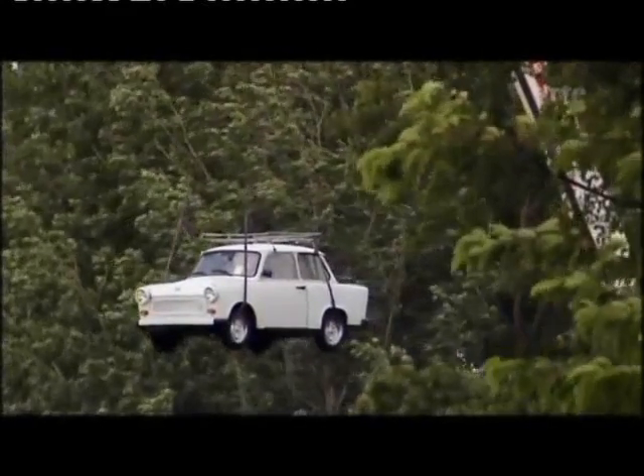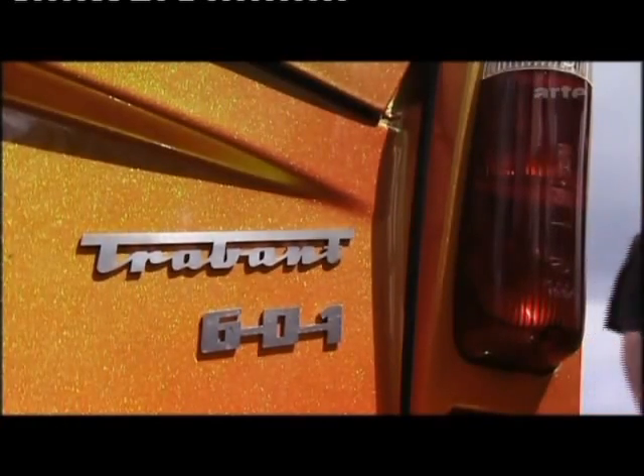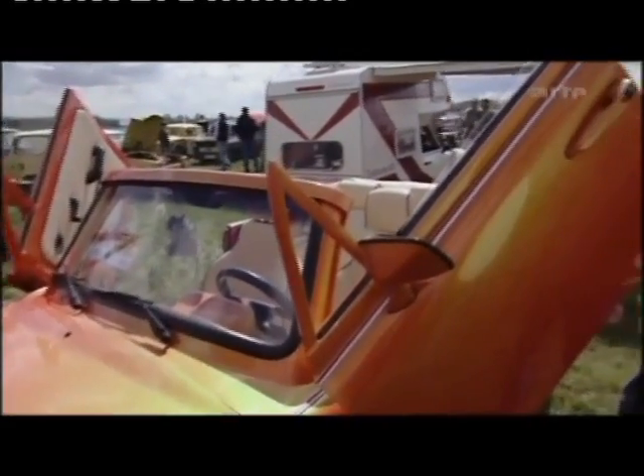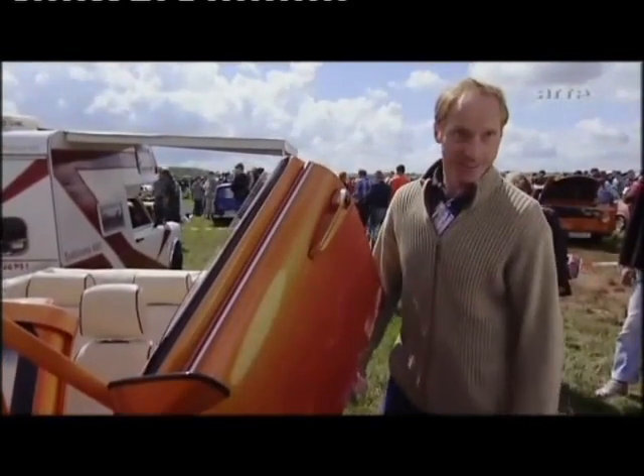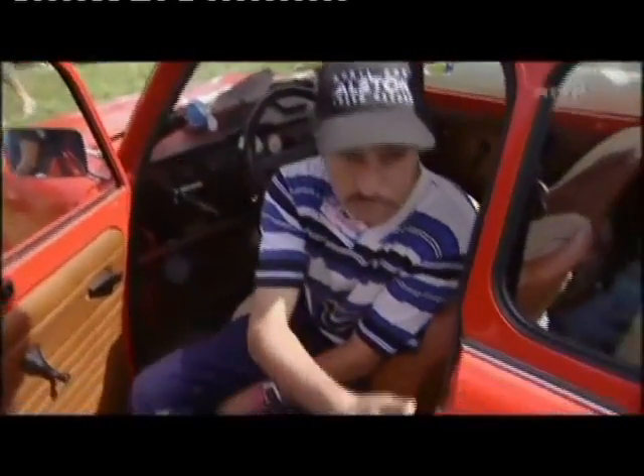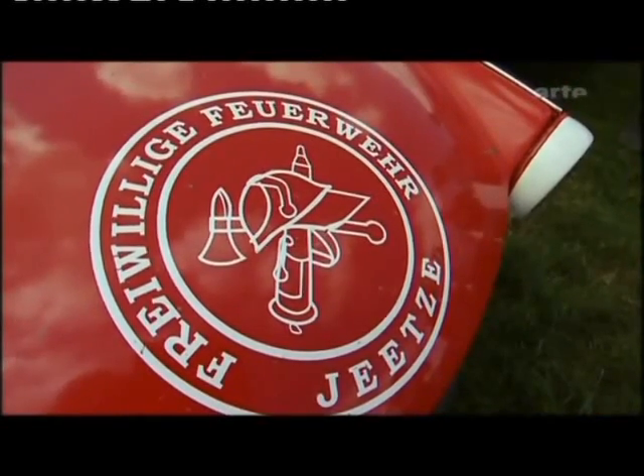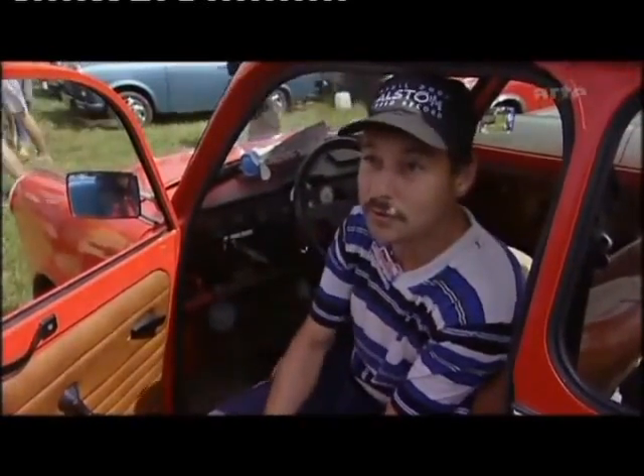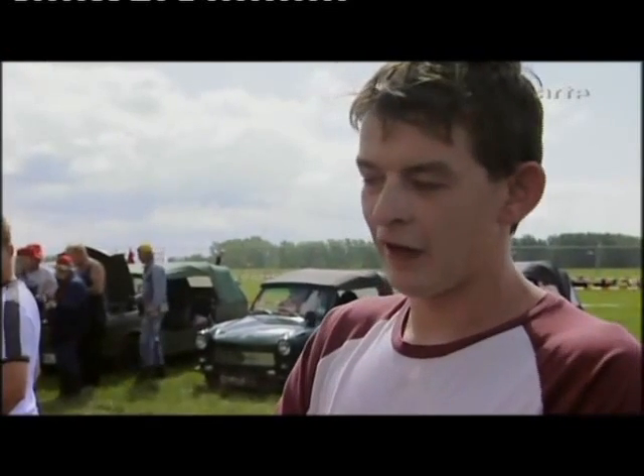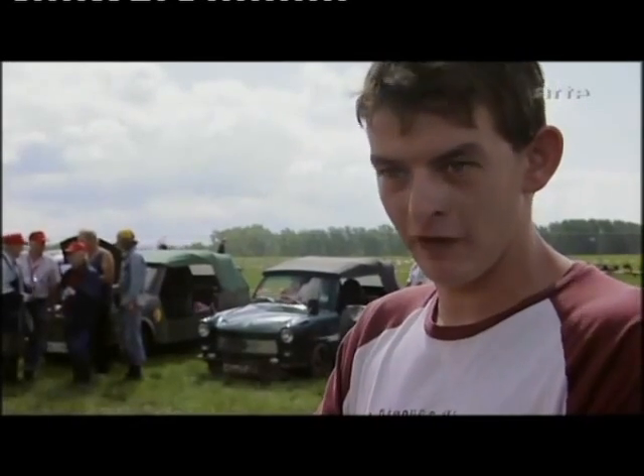Here is a famous product of plastics manufacturing: the Trabant. This iconic car of the former East Germany was born out of necessity and for nearly 40 years was the most coveted object for almost all East German citizens. Today it fascinates collectors. It is made from a plastic derived from cotton — designed this way by necessity, as East Germany had no sheet metal. The material is a mix of cotton and phenol resin in equal parts. A traditional weaving machine wove the thread, then the fabric was dusted with synthetic resin. The resulting mixture was layered on a conveyor belt up to about a hundred layers thick.